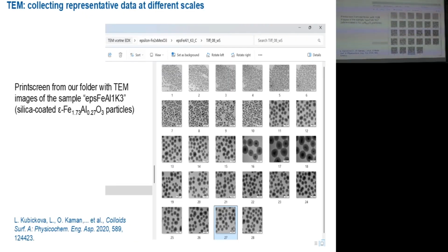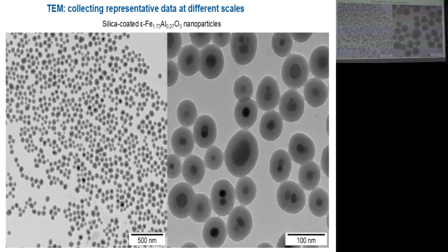So just some examples from our laboratory. All the time we are trying to do really representative sampling, representative imaging at different scales. So for example, in this case, it was a sample of epsilon iron oxide doped with aluminium, and it was coated with some silica. And this is just a print screen from our folder with TEM images, where you can see up to 30 images at different scales, with low magnification, where you can see a large number of particles, so you have really some representative idea about the sample, down to large magnification, where you can see some details. So try to do it like this. Try to get at least some images in low magnification, seeing a large amount of particles, and then these detailed images.